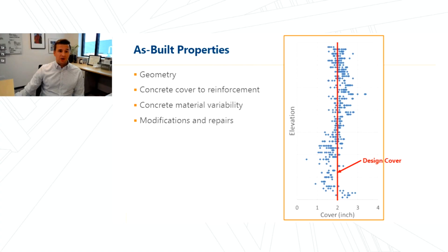And so verifying the geometry and dimensions of the elements is important. When we are considering the durability of a structure, the concrete cover to the reinforcement is an important property. And shown in the example here on the screen, we're showing a distribution of cover over the height of a cooling tower. And you can see this trend, and the as-built properties vary over height. In areas where there's lower cover compared to areas where there's deeper cover, these deviations from the design impact how we look at the structure and consider the progression of any deterioration.